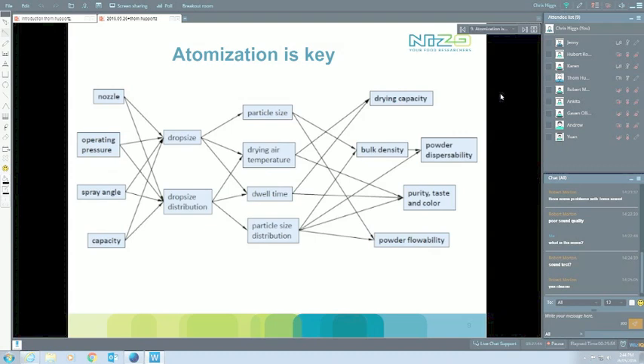That's really going to determine droplet sizes, but droplet size alone is not enough. It's really about droplet size distribution. So how wide or how narrow is that? That's going to be extremely important. That's going to determine the particle size of your powders. It's also going to affect your drying air conditions. That's going to affect the particle size distribution of the powders. And that relates to your drying capacity on the one hand, of course. You want it to be as efficient as possible there. Your bulk density and your powder dispersibility are going to be very much determined by the atomization. Also the purity, the taste, the color, and of course the flowability of your powder.